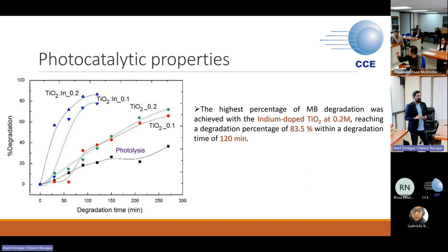That is the reduction of the band gap. Automatically, we suppose it has more electron-hole pairs, so you get higher activity. It's not the level that you introduced with the indium. It's the reduction. It's more convenient to use materials with less band gap. But there is a minimum band gap, because it should be activated with UV. So I suggest it should be between 3 and 3.5 electron volts. It's convenient because below 3 electron volts, it may not be activated by UV.